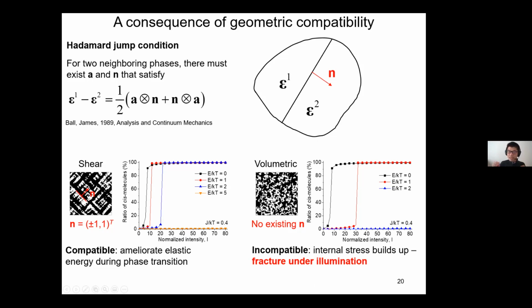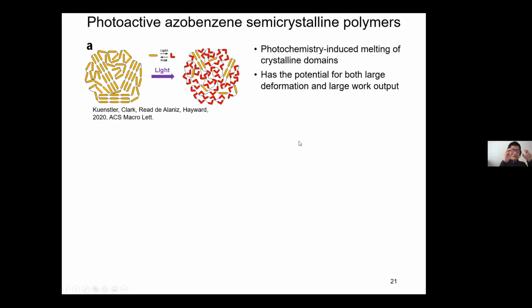So you see that the fracture probably doesn't only come from the defects, but also from the specific molecular shape before and after the photo strain, okay? Now we have this very nice, interesting observation.